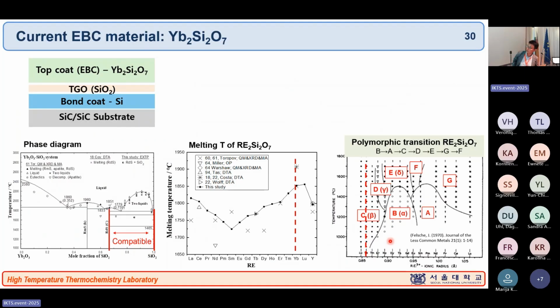So this is one of the examples. Yb2Si2O7 is one of the typical EBC coating materials, and on the bottom they have an SiO2 coating. These two have almost no chemical reaction, so there's no new phase in the middle. So it's stable at this temperature, and their melting temperature is about 1850. So it's quite stable up to this temperature range. And they don't have any phase transformation with temperature, compared to the other rare earth disilicates which have phase transformation. That's why they use the ytterbium silicate material here.